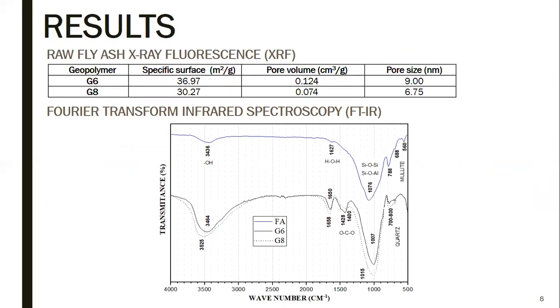Comparing between the two curing processes, we can observe that lower temperature leads to more specific surface, more pore volume, and pore size. The Fourier transform infrared spectra shows the bonds corresponding to mullite and quartz around wave numbers 700 and 800. Around wave number 1000 corresponds to silicon-oxygen-silicon or silicon-oxygen-aluminum bonds, which are the main bands of aluminosilicates. New bands found in geopolymers are oxygen-carbonate-oxygen bonds. This band indicates carbonation formed after geopolymerization.